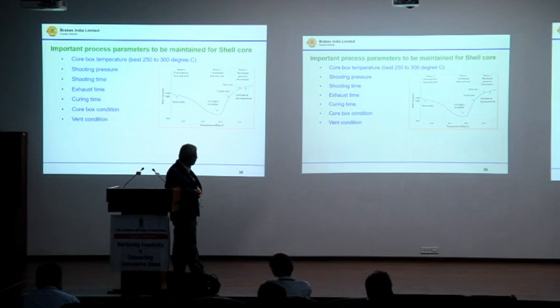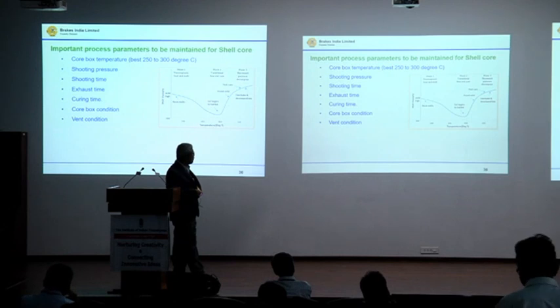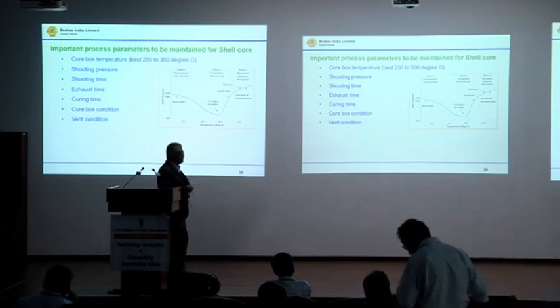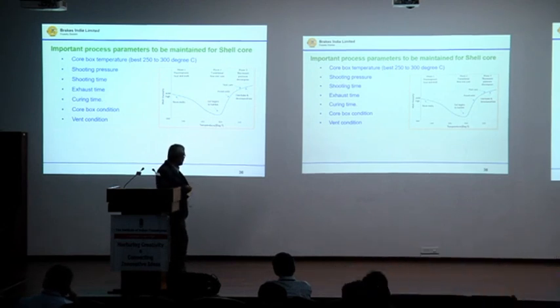This is the important process parameters. Core box temperature - its best range is 250 to 300, because if you maintain more than this, the resin melting time will shorten and it will not melt uniformly. Then shooting pressure, shooting time - these parameters are important, along with vent condition.